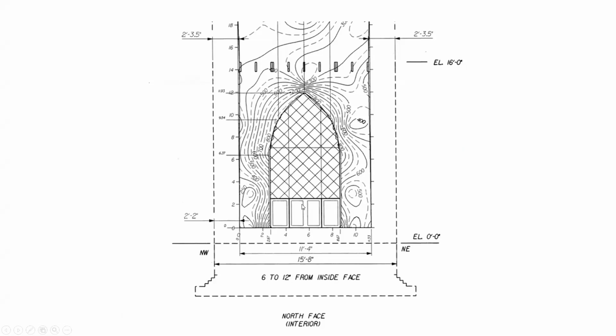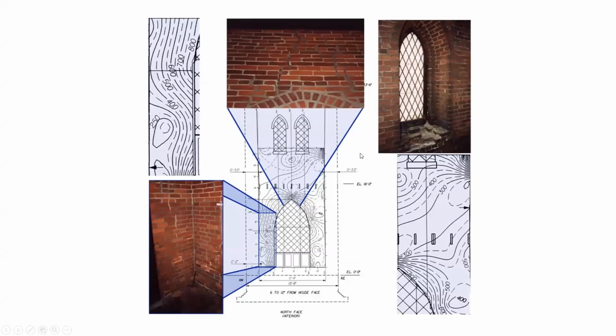So this shows a picture where you've got the arch shown and it's showing those strength contours from 300, in this case, to 600 PSI. So in this area with the damage, the strengths were definitely lower and more reasonable. And again, this is projecting and just showing those visible conditions in the photographs that you can see with the strength contours. And so the impact echo and the surface waves in particular allowed him to get a good handle on the existing stiffness, modulus, and strength of the masonry so he could model it for his retrofit design.